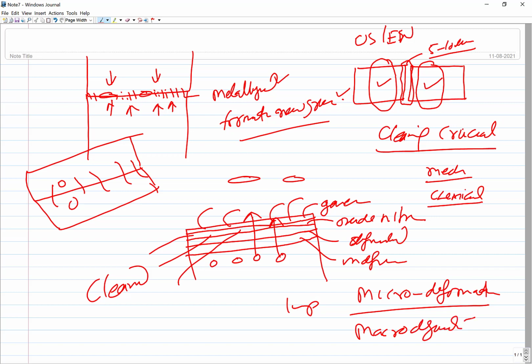Certainly you are getting your joint, like in forge welding. What you are doing is you keep on deforming the things so that there is metallic intimacy and closeness. But the joint is typically being formed primarily due to the interfacial closeness, not due to the deformation in nearby zones. So in friction welding, friction stir welding, or even in forge welding, there is a lot of deformation, but the most crucial deformation is the interfacial deformation. Okay, so the cleanliness and the interfacial deformation. The third aspect is the filler.